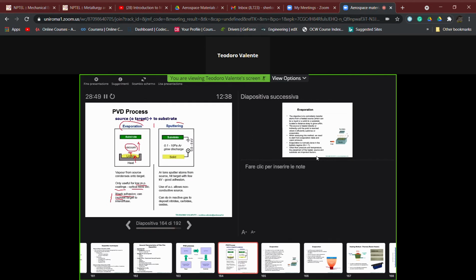The second class is sputtering, as we said. In this case, sputtering is made by the use, we will see the scheme better later on, of ions which are generated inside the chamber, for example, argon ions. These argon ions impinge on the solid, and then they sputter out atoms from the surface. And so in this case, we will have the atoms previously in the solid, which are sputtered out by the energy transfer due to the impingement of argon ions on the surface, and these represent the atoms which then will be condensed on the substrate.